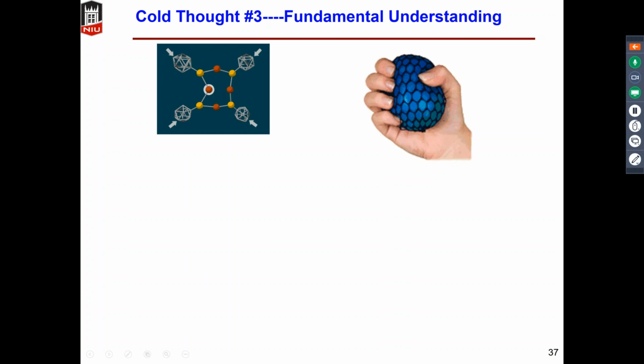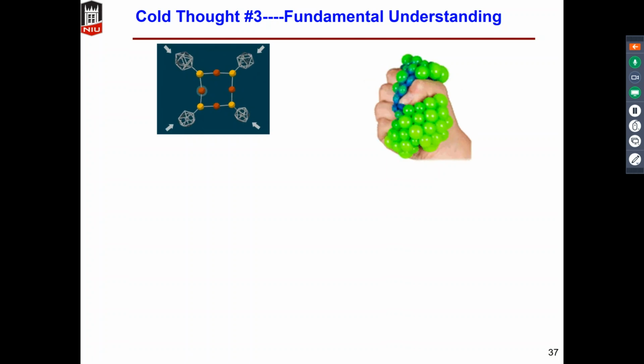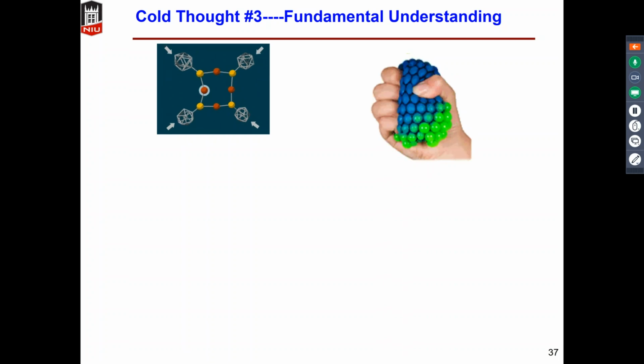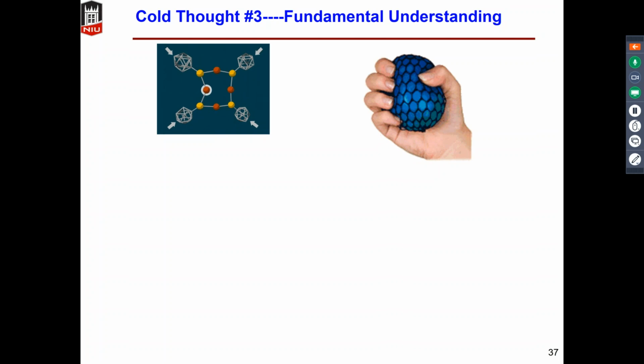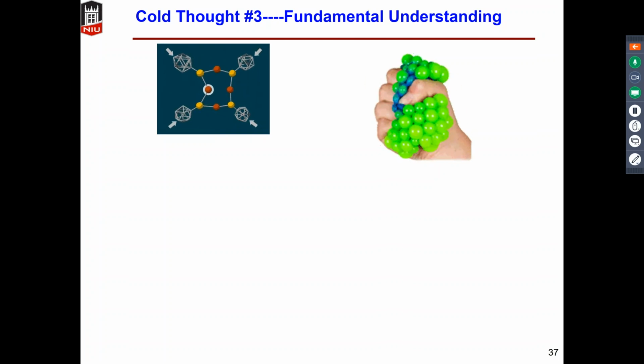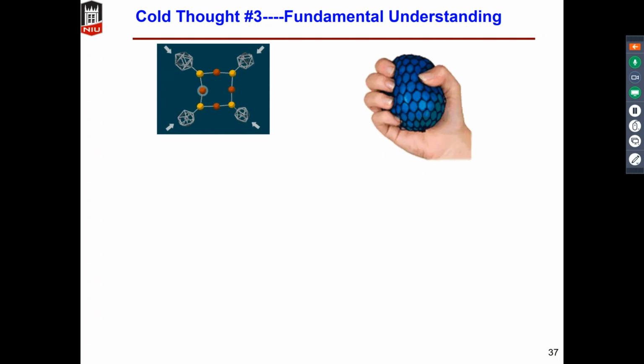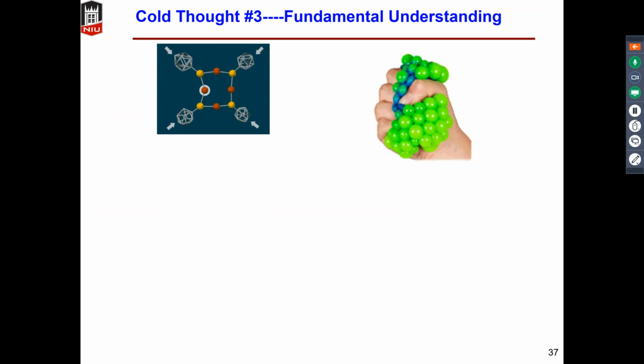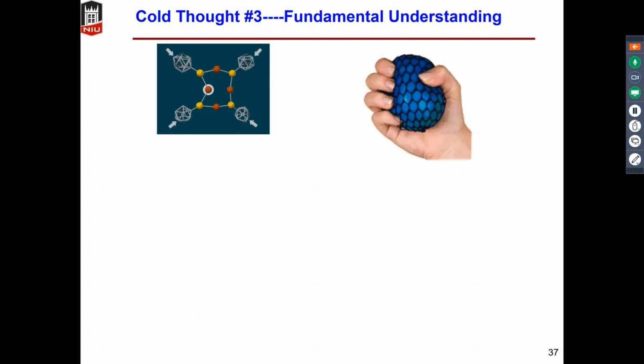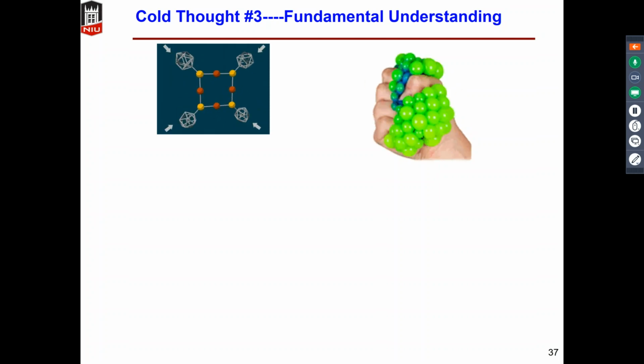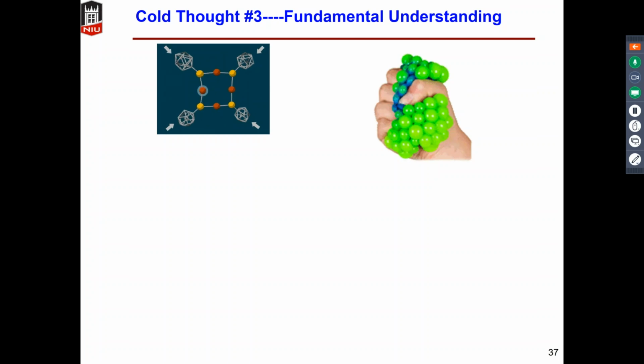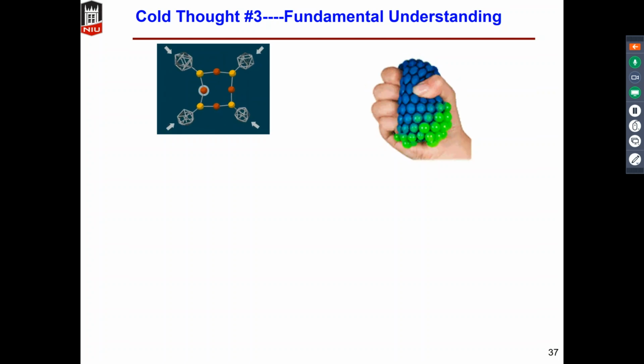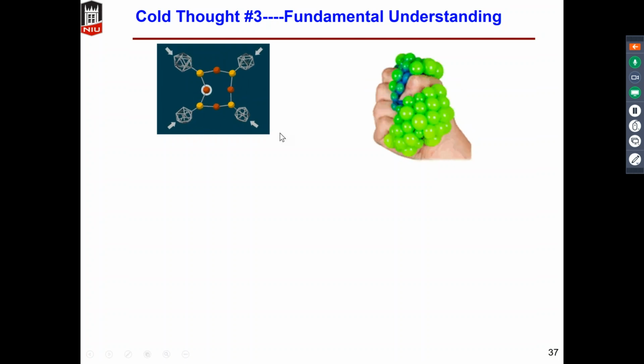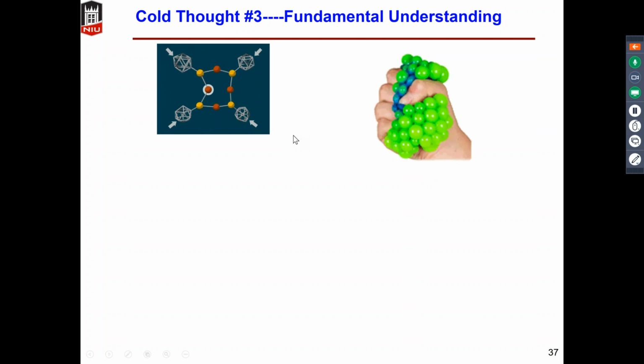Okay, so we further deepened our fundamental thoughts on this fascinating hybrid perovskite material. Many people like to use high temperature or low temperature or high magnetic field to torture this material. And here we chose a different approach. As chemists, we like to alter the bond length and bond angle to see if the property of the material changes. So we use high pressure to modulate the crystal structure of this hybrid perovskite material.